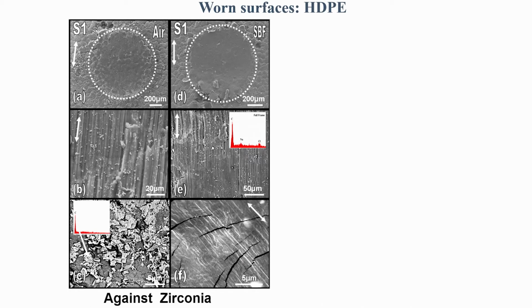Let us look first at HDPE, that is the S1 sample. In HDPE, you see there is a very clear signature of very deep abrasive grooves and scratches observed in ambient conditions. In SBF, the scratches and severity of abrasion is reduced, but more interestingly there is some concentric cracking observed on the fretted surface.